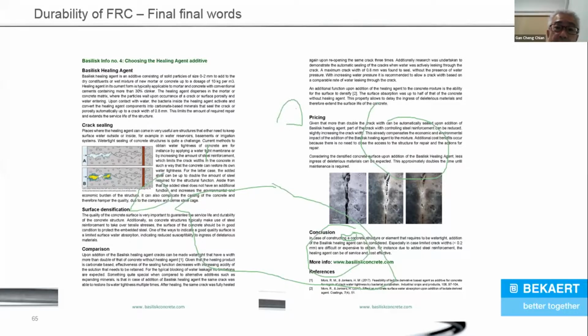What has happened is the bacteria is activated after you add water. And when the bacteria is activated, it starts to eat something. When it starts to eat, it will start to pass motion, and the pass motion is the product that seals up the cracks. So it will heal the cracks. This is what they call self-healing concrete. And this is the best product that I have ever seen being introduced in this last 2 or 3 years. It's not heavily used yet, but it's an amazing product.